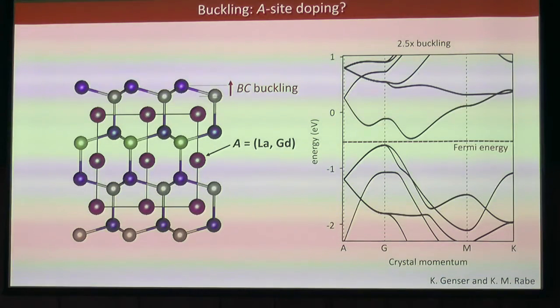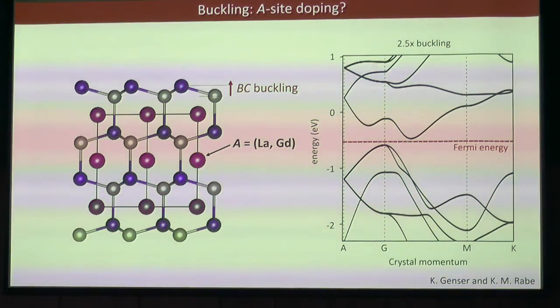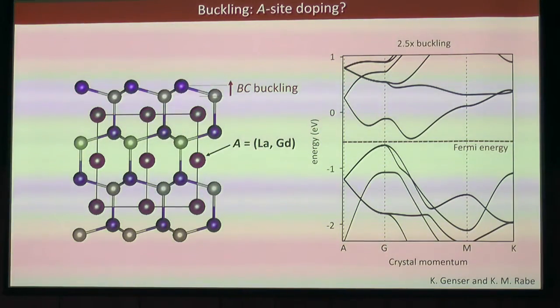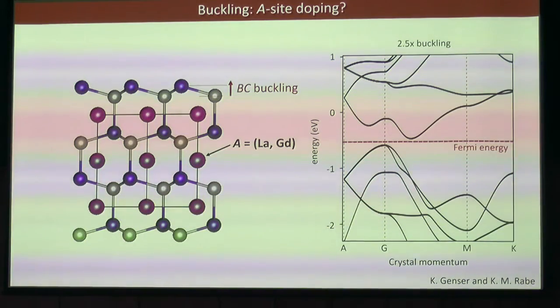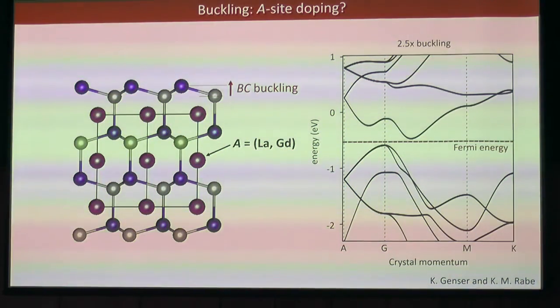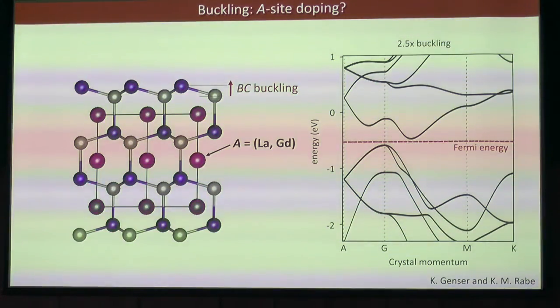All right, so what we actually want to do is take these compounds and see if we can induce some structural distortion to see if we can open up a gap, right? Again, our target is to hit about a 2.5 times enhancement of the buckling magnitude. One way we've decided to go about this is to start substituting on this A-site cation. Our baseline compound is lanthanum, which has a really large cation radius, but there's a well-known lanthanide contraction. So let's take a cation like gadolinium. If this is smaller, the basic idea is that the C-axis separation goes down. You have enhanced layer-layer interactions that should enhance the buckling. Okay, and that's indeed what we see.